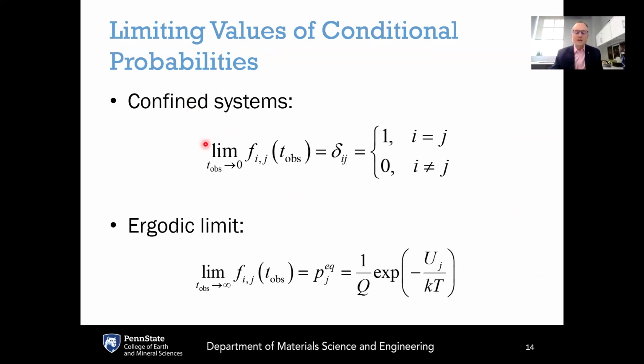If you have a fully confined system, say the limit of observation timescale going to 0, the conditional probabilities become a Kronecker delta function, delta ij, which is equal to 1 if i equals j, or equal to 0 if i is not equal to j. So for a fully confined system, transitions are not allowed. And the ergodic limit, according to the ergodic hypothesis, so this is the limit of an infinite observation time, then the Fij's become the equilibrium Pj's, where this no longer depends on i at all. This is just the equilibrium probability of occupying microstate j, and that is given by 1 over the partition function. Partition function is just the normalization factor for the probabilities, and then this Boltzmann probability factor, e to the minus uj, which is the energy associated with microstate j, divided by kT.